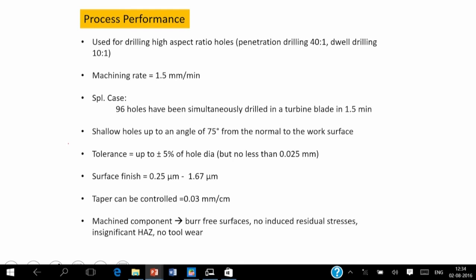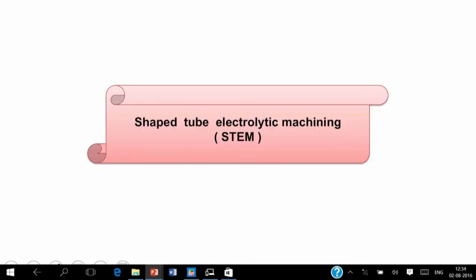So now another process is there, that is called shaped tube electrolytic machining, STEM. In electrostream drilling we have seen the aspect ratio of the holes is maintained at 40:1 maximum. But in case of shaped tube electrolytic machining, the aspect ratio of the holes is maintained at around 300:1. So it is very high.